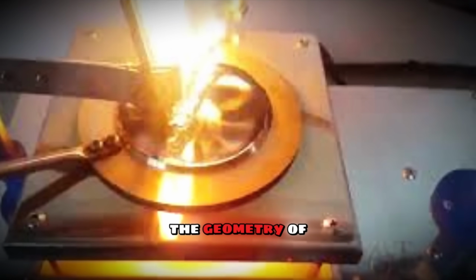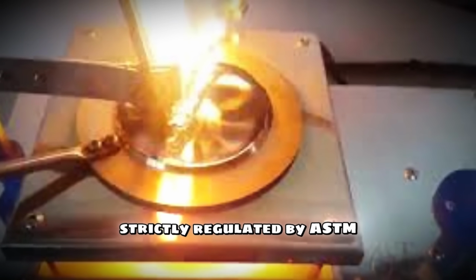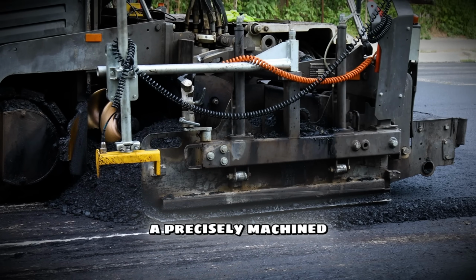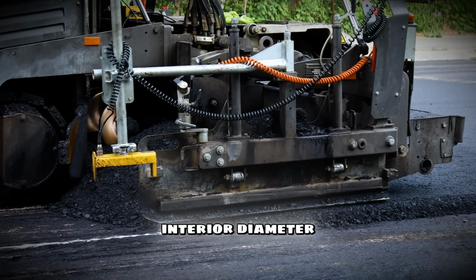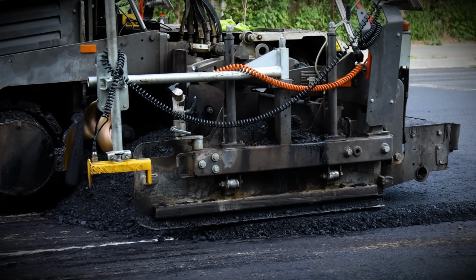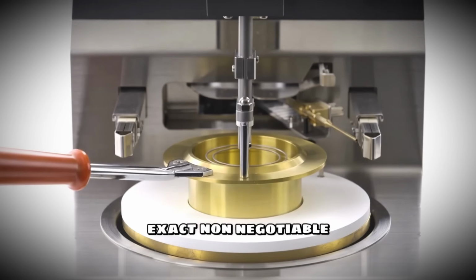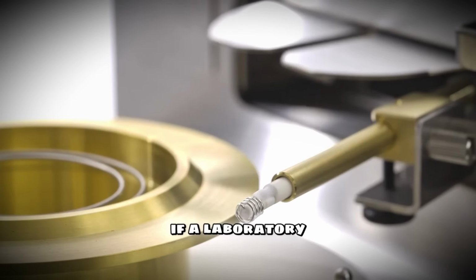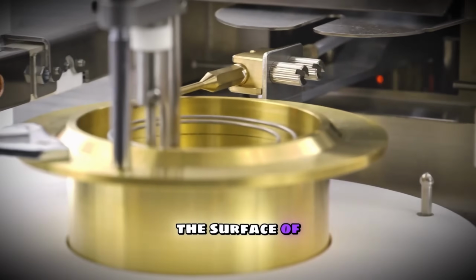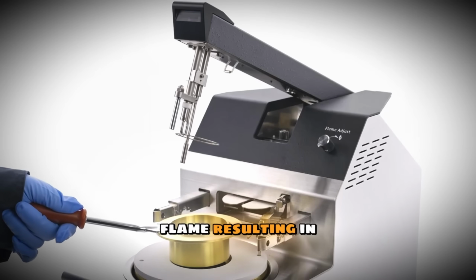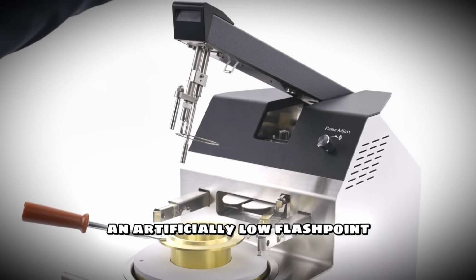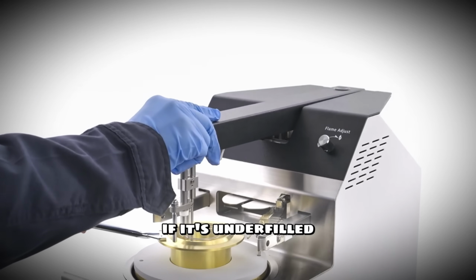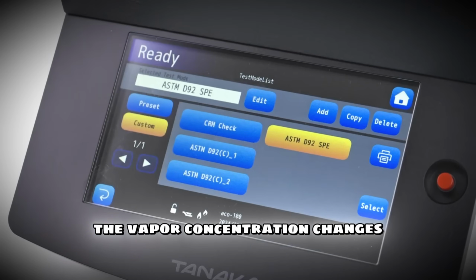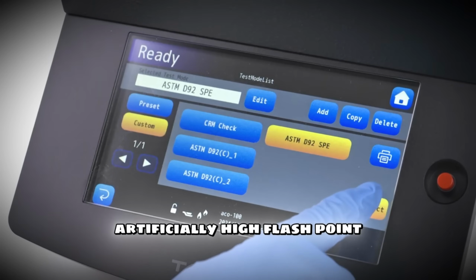Furthermore, the geometry of this cup is strictly regulated by ASTM standards. It has a precisely machined interior diameter and a specific depth. Inside the cup, there is an exact, non-negotiable fill mark. If a laboratory technician overfills the cup by even a fraction of an inch, the surface of the asphalt is too close to the test flame, resulting in an artificially low flash point. If it's underfilled, the vapor concentration changes, leading to an artificially high flash point.